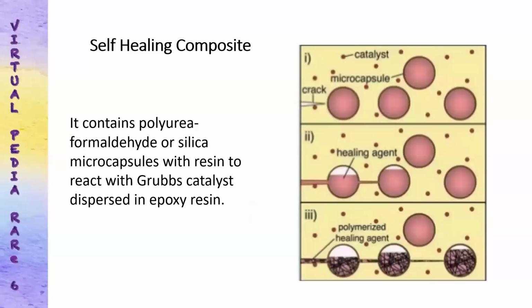The latest advancement in composite is the self-healing composite. Self-healing composite contains microcapsules of polyurea formaldehyde or silica, which contains resin. Under stress or crack formation, this capsule bursts, and as it is burst, the resin is released from the microcapsule. There is a catalyst in the epoxy resin which causes polymerization of the released resin from the microcapsules, and it fills the gap. So this is a self-healing composite which can handle the crack or fracture of the composite.